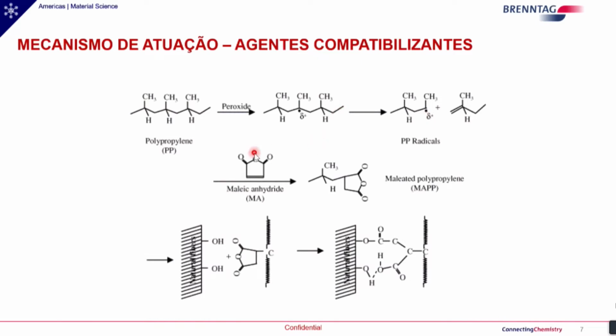So what is the crux of the matter with this molecule? The molecule has an apolar phase in its structure, only with carbon and hydrogen. And we see this highly polar phase here, as you see with the laser pointer, due to the oxygen that is part of its very structure. So here we do the following. We have a polypropylene that was modified in its structure, and it goes from an apolar to a polar material, as we can see in this example right here.